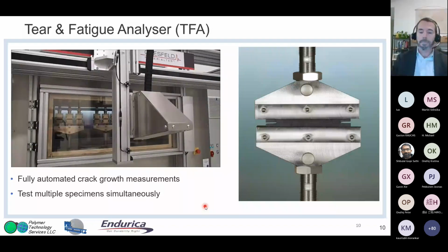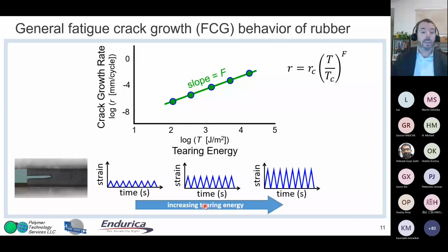So you take that information and you would vary how much the crack is opened, small amount, larger amount, even larger amount, and that can be then converted to a tearing energy, and then allowing you to plot the crack growth rate versus tearing energy like I showed earlier. And it typically shows this power law response with an exponent F. And so this is the fatigue crack growth testing that's typically done.